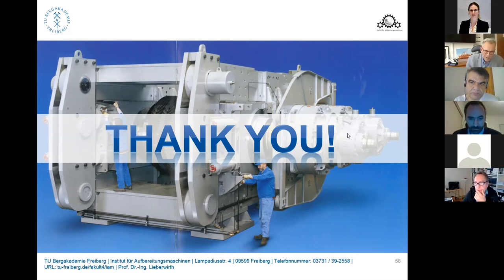I'm not quite sure whether I caught your question correctly, but for sure, if you crush or grind a material down, you have to go first to the liberation particle size, and you have to grind it down. And the question is always, if you have a confined particle bed, whether you achieve a selective comminution there. I would be cautious, because you have to have a very thin particle layer there. And I think without shear loads, it might be difficult to achieve a liberation size of less than 45-50 microns. So that's why I would expect you need to do something there.